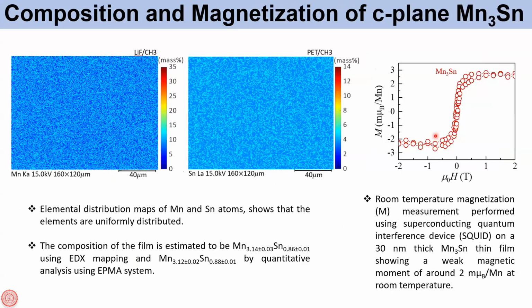Subsequently, we also did a composition mapping to confirm that we have formed the perfect stoichiometric composition and that there are no clusters of manganese, because that has been reported in the literature. We see that the manganese and tin distributions are rather uniform throughout the film, but there is a little bit of excess manganese. It's not that much, but there is a little bit of excess manganese present in our films. And this magnetization measurement shows that the magnetic moment is really, really small.